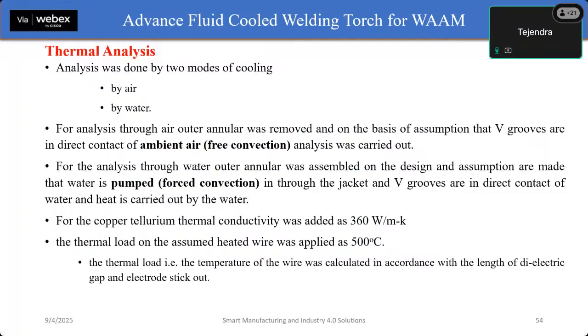The thermal conductivity of the copper tellurium was considered to be 360. So a thermal load of 500 degrees was applied to the assumed heated wire. The thermal load, that means the temperature of the wire, was calculated based on the length of the dielectric gap and the electrode stick out. The dielectric gap is the gap between the two polarities that we have provided for the preheating of the wire.